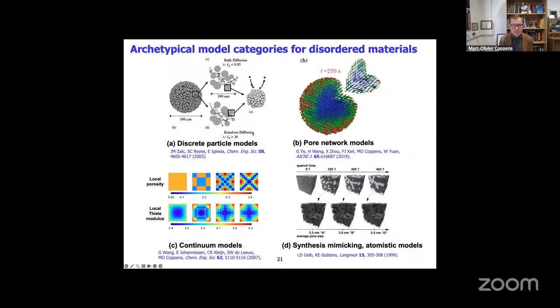We have these discrete models. They can be discrete particle models. This is an example from the work of Enrique Iglesia and colleagues, where they looked at a pellet containing particles, and then they can start using kinetic Monte Carlo simulation to look at how diffusion happens through the pore space in between these little spheres. And you can have a particle size distribution even, and look at situations where the mean free path is either much smaller than the average chord length here, or is of the same order of magnitude or larger, hence bulk diffusion or Knudsen diffusion, and start to see how the tortuosity and the effective diffusion properties depend on the conditions.